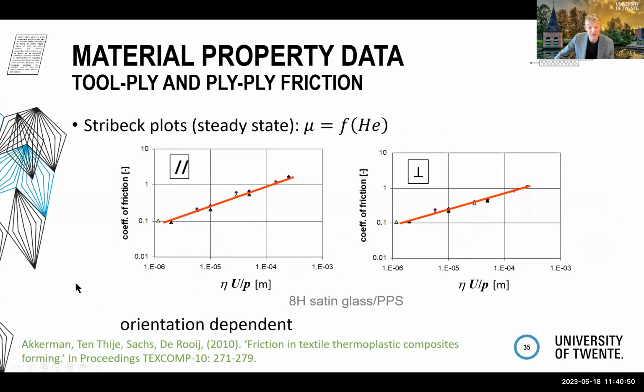It does, by the way, also depend on the fiber orientation. So if we use a Stribeck curve, plotting the coefficient of friction against the Hersey number, in one orientation we get more or less this behavior. It nicely works with this Stribeck plot, by the way, for the fabrics. If we change the orientation of the fibers, so get a more transverse sliding, then we do see some effect on the coefficient of friction. Mind, these are logarithmic scales, so in absolute numbers, the differences are quite more significant.